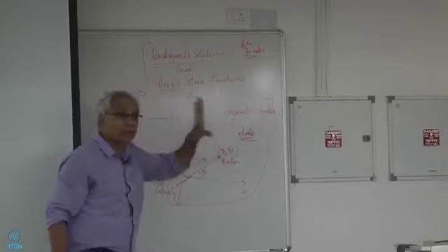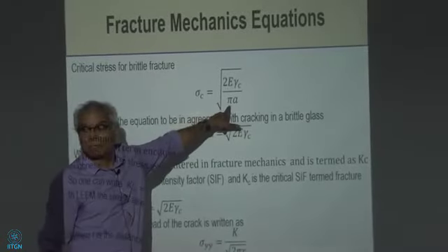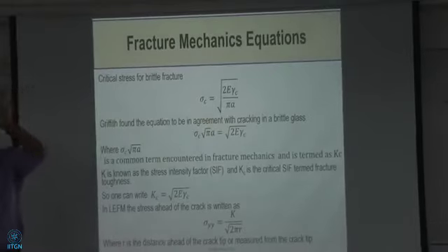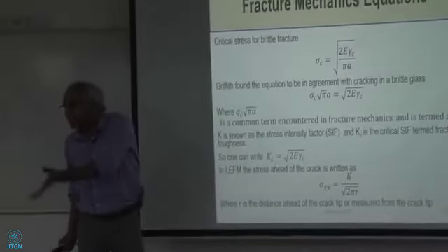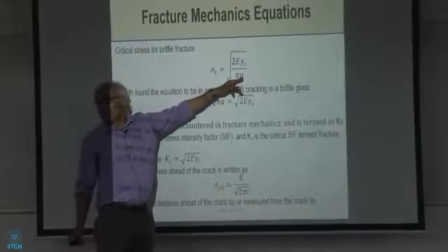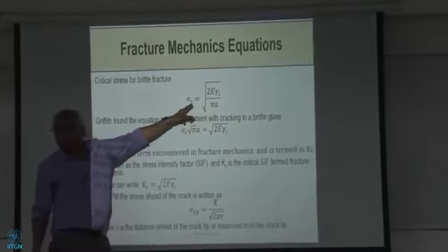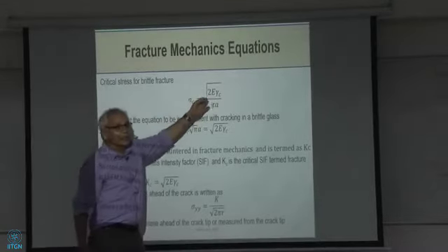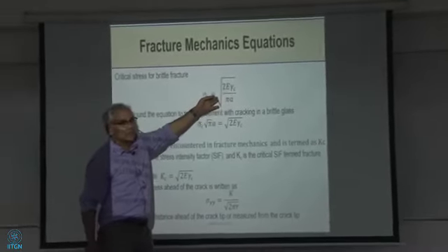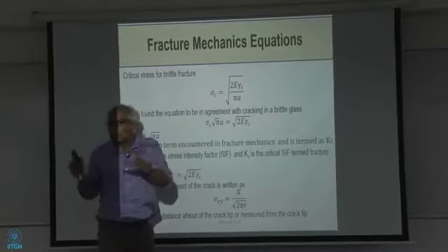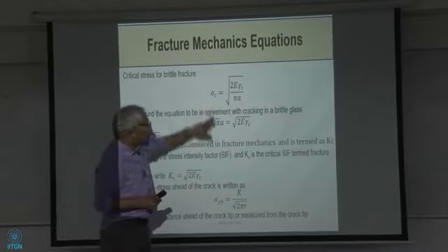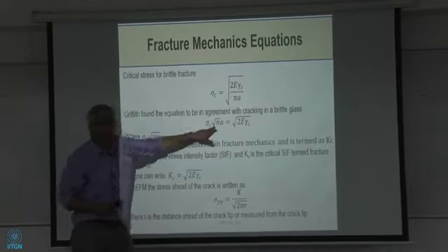So Irwin was the guy who said, you know what, I'm finding something in the literature that I can relate, this equation looks very interesting. Especially it started to look very interesting when Griffith got his results this way. So when Griffith said, hey, I'm getting some results on glass, which is very brittle, totally elastic. When I put a scratch, which has got a length a, and if I put a stress sigma, I get this equation. You know, you can plot this equation. And look at the similarities. They start to compare the similarities. Sigma times square root of pi a